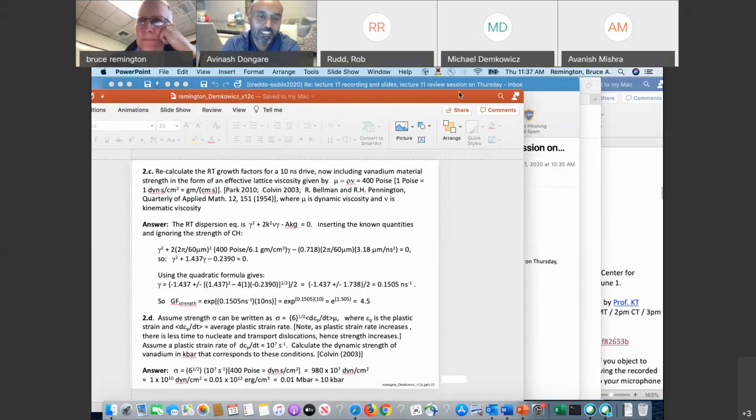Yeah, because we are running some simulations of copper iron composites. And what we see is iron will undergo a phase transformation, but when there's a reverse phase transformation, you actually see twinning for certain orientations. And so for us it's a little interesting as to how somebody would come up with strength characteristics or strain hardening mechanisms when you have these complex features, either phase transformed regions or distributions of twins. Okay. It's really interesting.